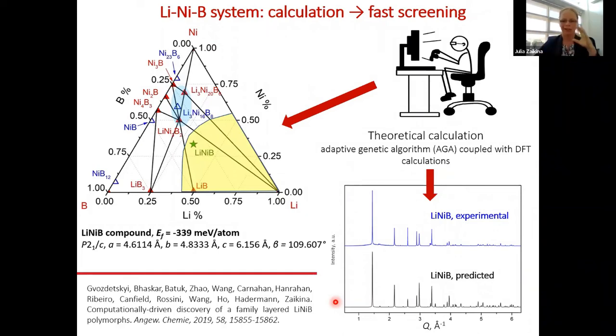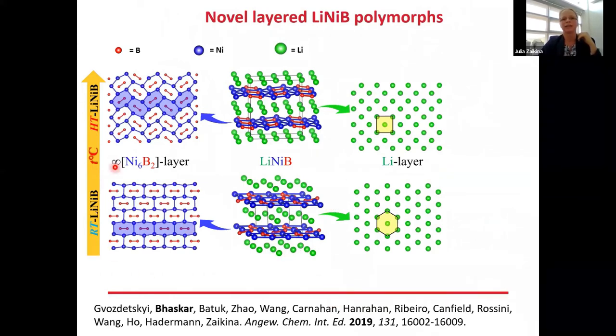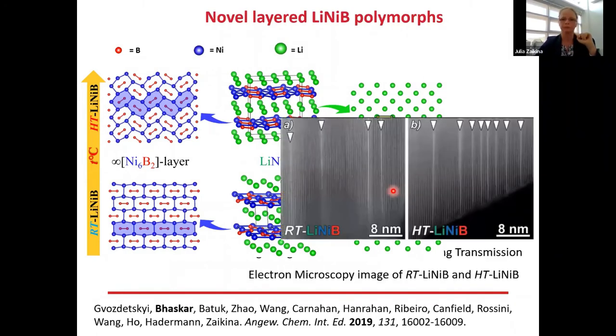However, of course, the reality is often more complex than the prediction. So theoretical methods can predict this room temperature polymorph, but if we increase the synthesis temperature, the structure transforms to the high temperature polymorph. First of all, it's a layered compound, which is very rare among those borides. Secondly, it has a lot of lithium stored between the nickel-boron layers. So we have the nickel-boron layers with a different topology depending on whether it's a room temperature or high temperature polymorph. And then we have a lithium layer sandwiched between those nickel-boron layers. And the lithium layer adopts a different configuration depending on the polymorph. And again, we confirm it with scanning transmission electron microscopy.